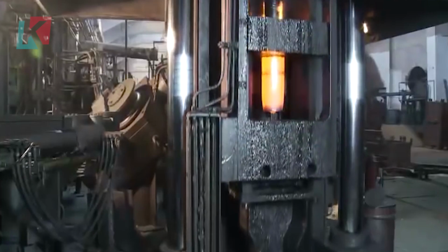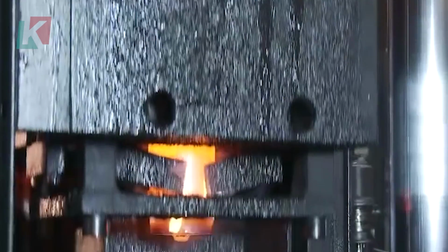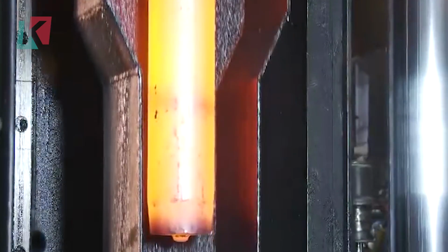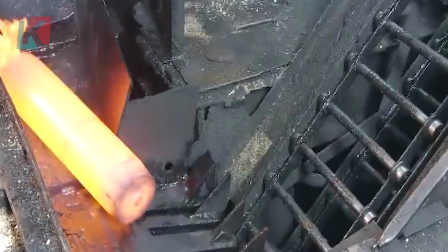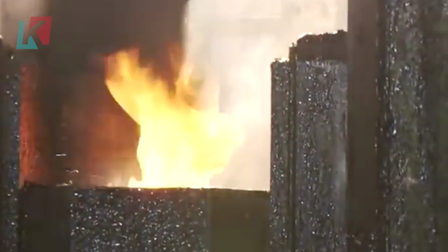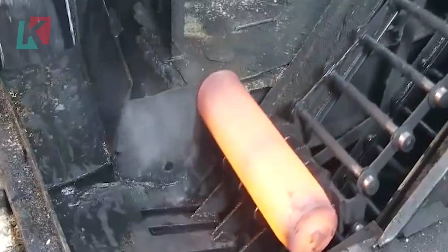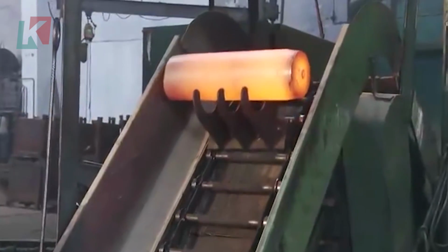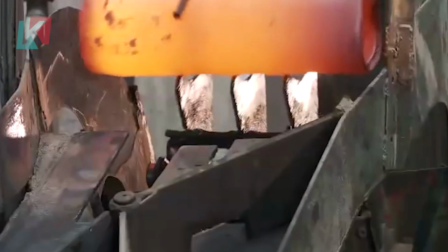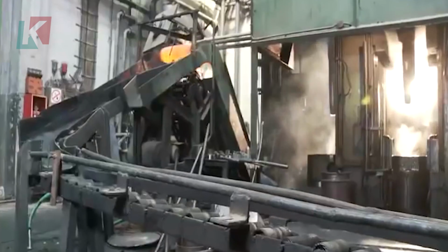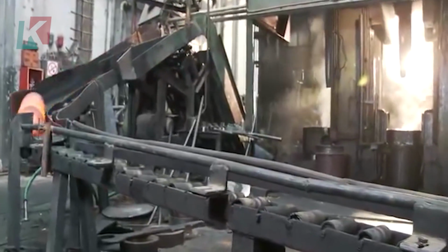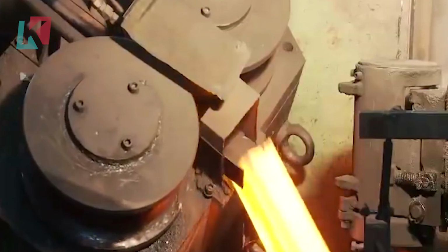The press's computerized control system monitors force, displacement, and timing to within milliseconds, ensuring each shell meets exact specifications. Temperature monitoring continues throughout the process using infrared pyrometers. If the workpiece temperature drops below 1050 degrees Celsius, it must be reheated to maintain proper material flow and prevent die damage. After forging, the shells undergo controlled cooling to room temperature, followed by stress relief heat treatment at 650 degrees Celsius for 2 hours. This eliminates residual stresses from the forging operation.